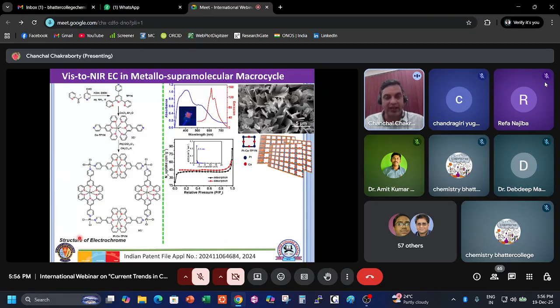Emission is actually very unique for this kind of platinum complex. What is happening is that we prepared the cobalt complex first, and then we use a platinum complex to join the cobalt complexes into a square, basically a square shape. So this platinum complex is very unique if it can have some aggregation inside.